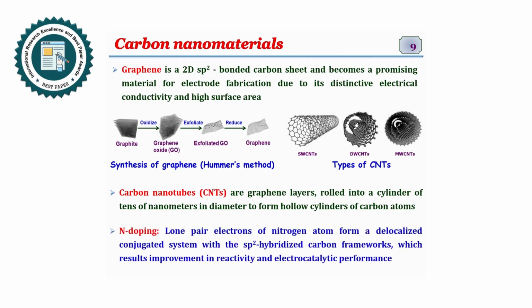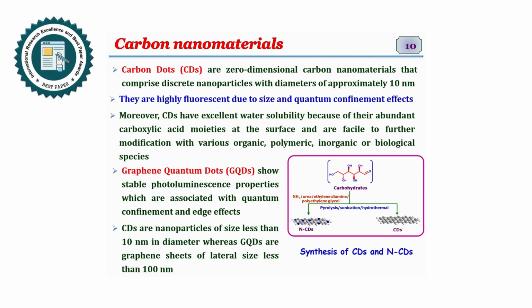An important property in carbon nanomaterials is doping. Doping of heteroatoms, nitrogen, sulfur, phosphorus, into the carbon skeleton leads to a change in their physical properties like electronic and electrical properties. Especially the lone pair of the nitrogen atom forms a delocalized conjugate system with the sp2 hybridized carbon framework, which results in improved activity and electrical conductivity, leading to different electrocatalytic performance.